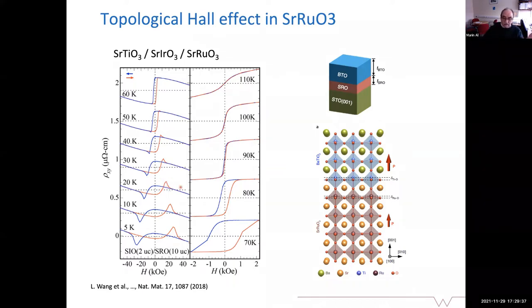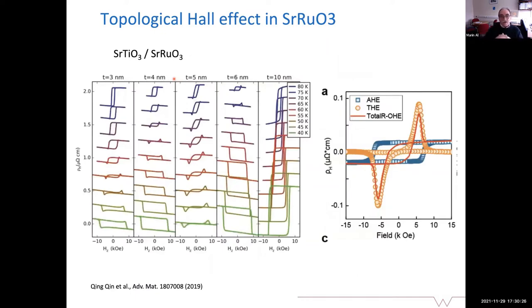some abnormal scattering does occur, and this scattering is always associated with such a jump in the Hall resistivity. And you see here that this evolves with temperature, it becomes more significant at lower temperature. This was thought to be a result of interaction between strontium iridate in this case and strontium ruthenate. Strontium iridate, due to iridium, has a fairly large spin orbit coupling, which may induce the Dzyaloshinskii Moriya interaction, and I will show you later. That happens also on plain strontium titanate, and that was a surprise.